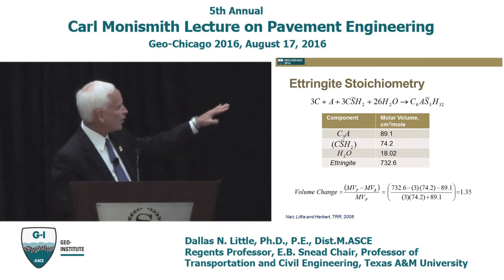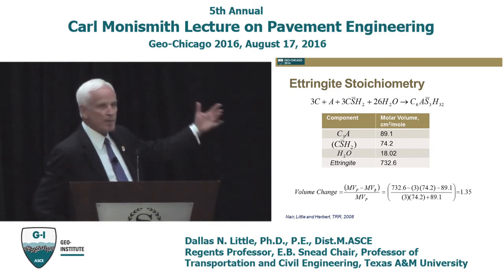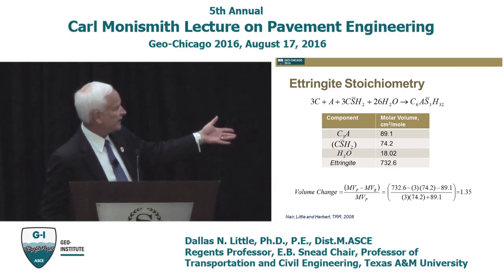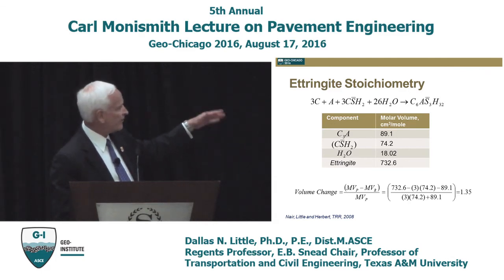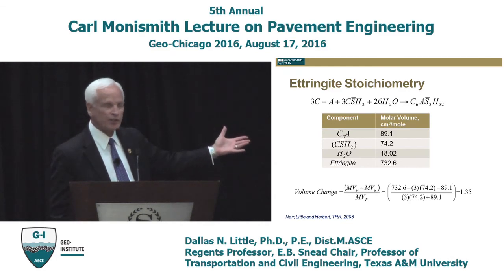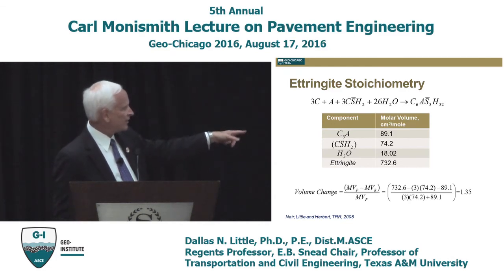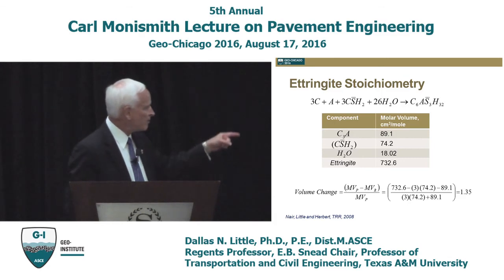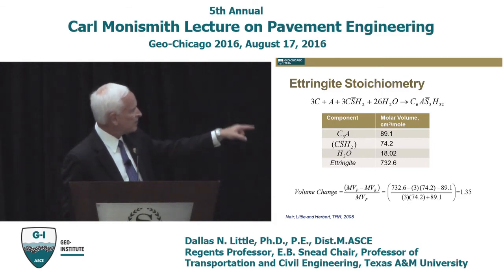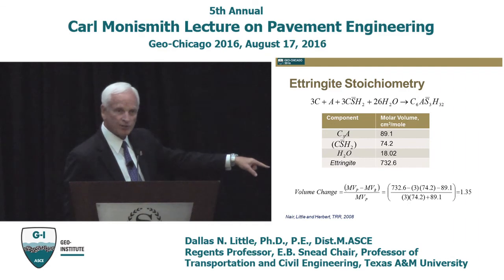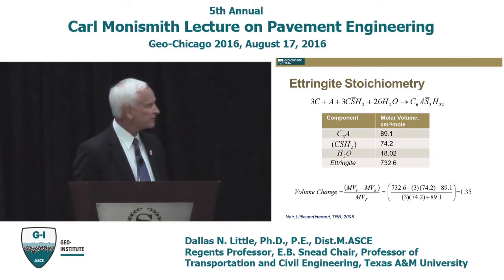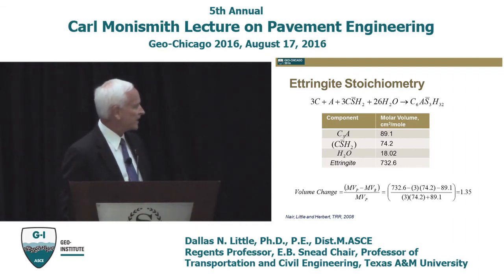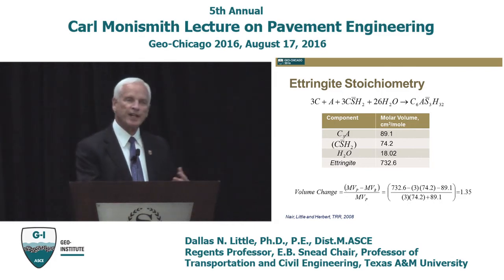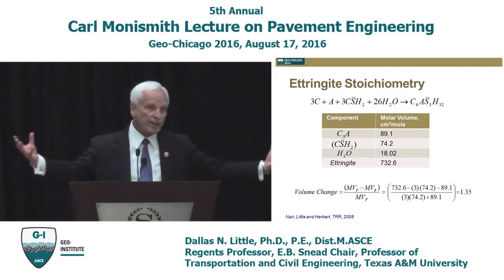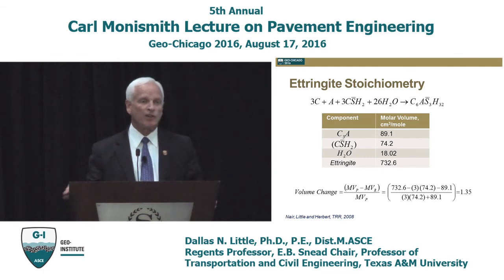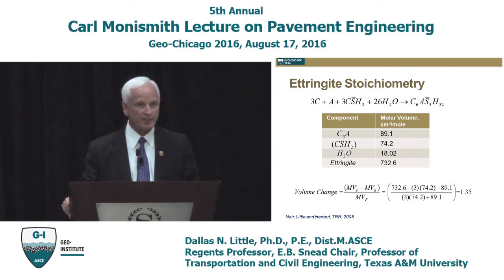We know the chemical formula for ettringite. We know how many moles of each component are in there. We can look in the literature and find the volume of a mole of that component, so we can calculate the volume change. It's simply the molar volume of the products minus the molar volume of the reactants divided by the molar volume of the reactants. And when you go through that calculation, you find that if ettringite is fully activated by water coming in from the outside, you get a volume change of 135%.